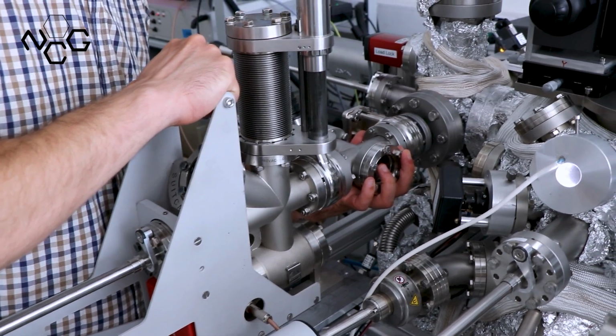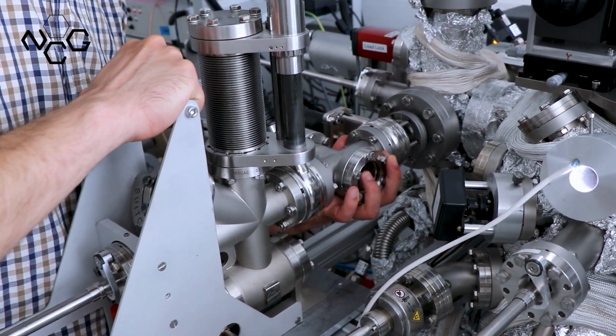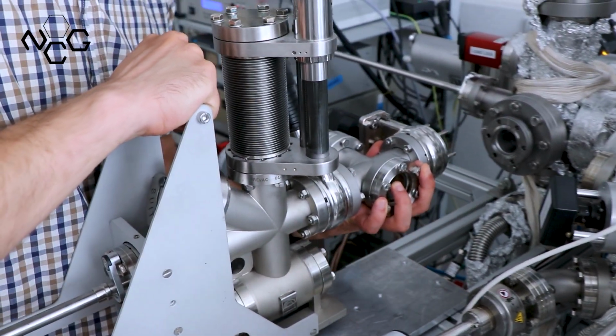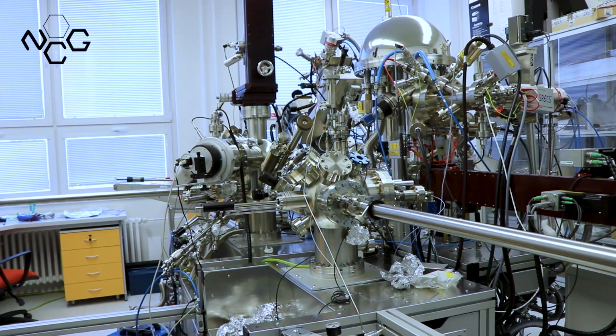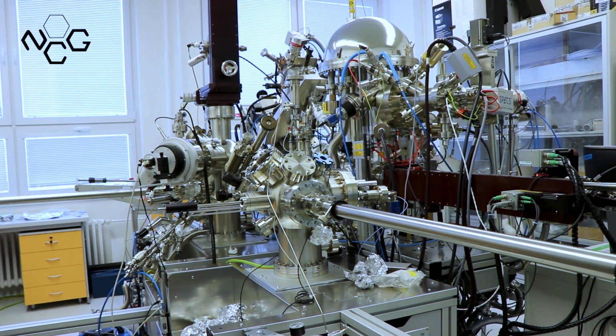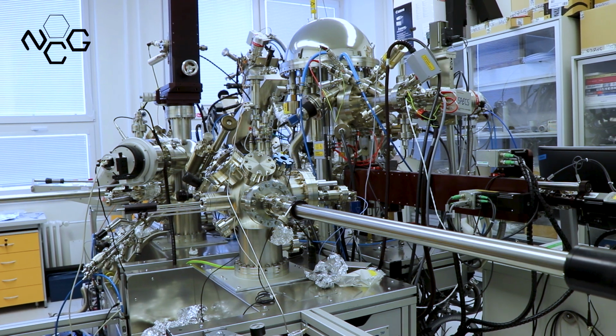As mentioned before, we can also transfer the samples to other UHV systems without breaking the vacuum, by using a suitcase. This way, we could also measure XPS and LEED, which further confirm the quality of our MoS2. So, with our UHV exfoliation system, we can prepare monolayers of MoS2 and other 2D materials. This way we can perform fundamental studies of these materials in pristine conditions using different state-of-the-art techniques. This is a prerequisite for an in-depth understanding of their physical properties and potential applications.